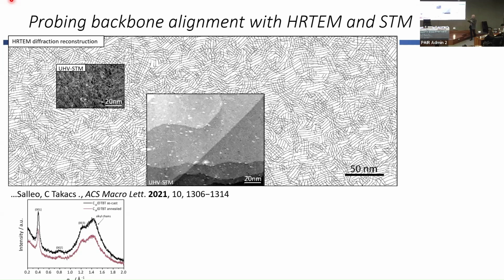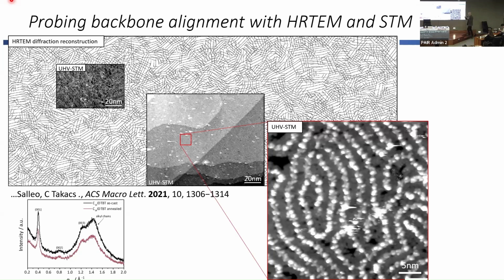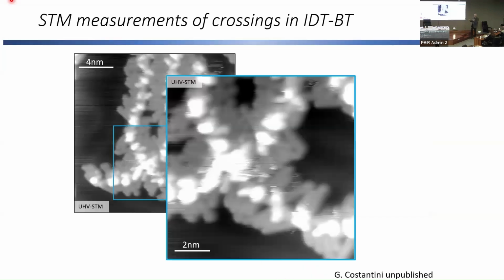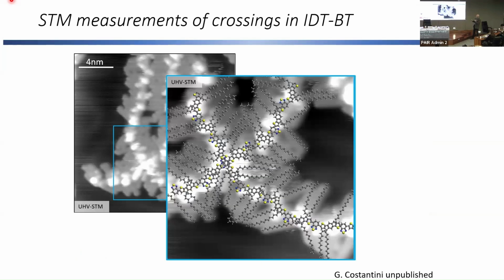So we then went back to the STM and had a look. Remember, I told you that the electrospray technique forms a monolayer, but there are some instances where you have over-crossing between two adjacent chains. And this backbone crossing was very consistent. And so we had a look at this, and you can see these crossing points. And we overlay the polymers so they fit perfectly on the STM. And you can see that this crossing only occurs at this space here. This is our benzothiadiazole unit. So what the side chains have done in this instance is they've pushed the crossing points to the part of the backbone where there is no side chain. So it's only at this point that we see this happening.